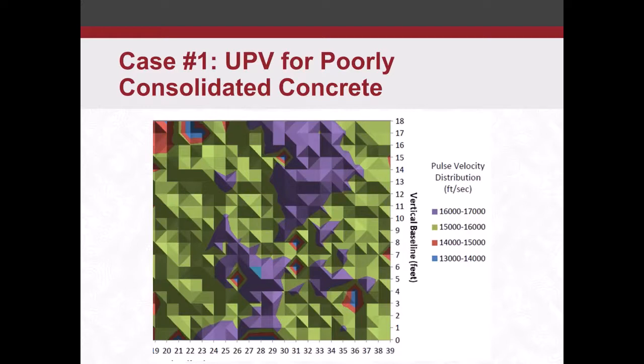But I mentioned we compare adjacent test points. So if you look specifically down here at the bottom, we've got blue as our lowest wave velocity, purple is our highest wave velocity. From one point to the next, we're going from the extreme. We're going from about our lowest wave velocity to our highest wave velocity on some of these adjacent points. So these are areas that we would flag as anomalies. An area right here perhaps is an anomaly. These two spots right here are actually pipe penetrations, so there was no data gathered here. But this would be an anomaly up here, and potentially an anomaly over here.